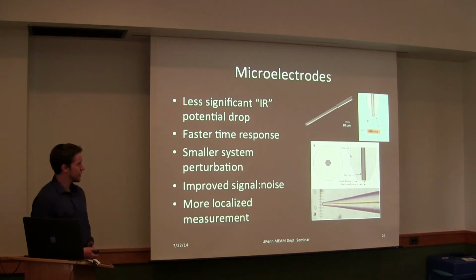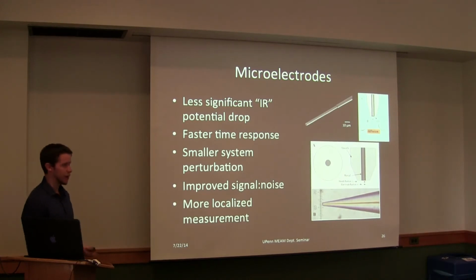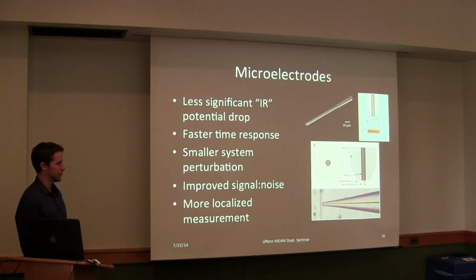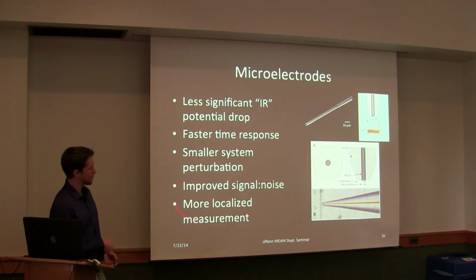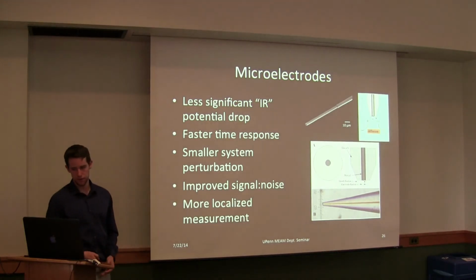So microelectrodes are very nice because you get a less significant IR potential drop in the solution, which is due to the solution resistance. We get a faster time response due to the much smaller size, which has a smaller capacitance. There's a smaller system perturbation, so you don't deplete concentrations in the solution as drastically. We get improved signal to noise and a much more localized measurement. So these are all the reasons why people move towards microelectrodes.